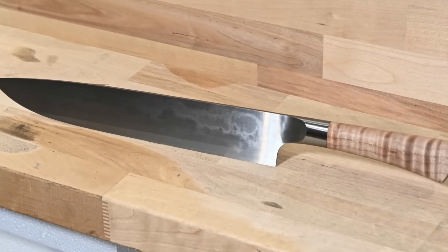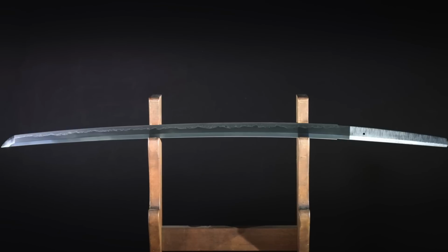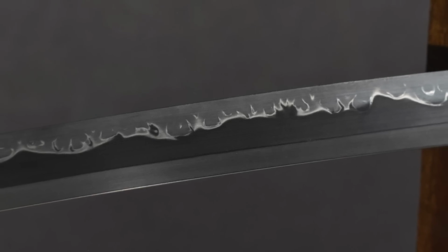So, as I mentioned earlier and showed in the thumbnail to this video, this blade came out with this wild cloudy look. For many of you, this will be pretty familiar. It's a hamon. In the Japanese sword world, you get them by claying up the blade and going through a process that produces them in a fairly controlled way. Now, the reason for this, without getting too deep into the metallurgy, is that when blades are cooled from what's known as austenitic condition, which is generally north of 1500 Fahrenheit or so, to a much cooler temperature, they'll change their molecular structure to what's known as martensite, which is the hard form of steel that you need for cutting tools. Now, here's the tricky part.